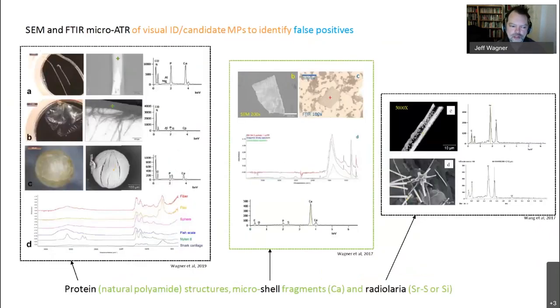And then sort of as the complement to screening for microplastics, SEM is very useful for screening out false positives. Very quickly, not only with the X-ray detector, which can identify inorganic false positives, but also with the backscatter detector in an SEM, you can very quickly separate the dark particles, which are either biological or polymeric, versus the bright particles, which are inorganic. I'm sure many of you are aware of the false positive potential of mineral-based particles such as shells, calcium oxides, aragonite, like you see in the middle.